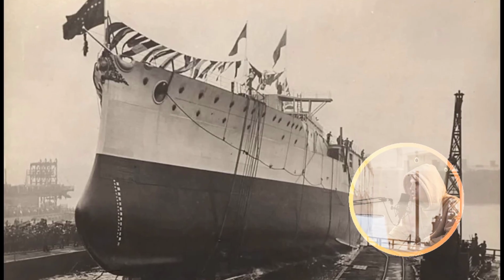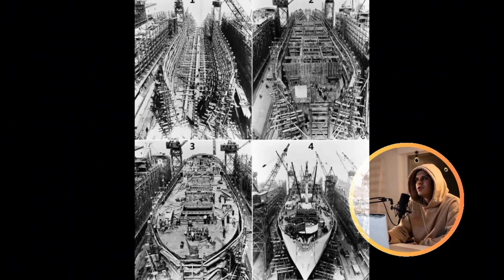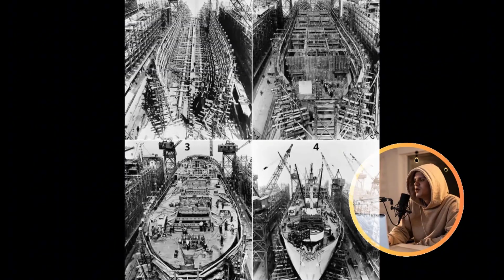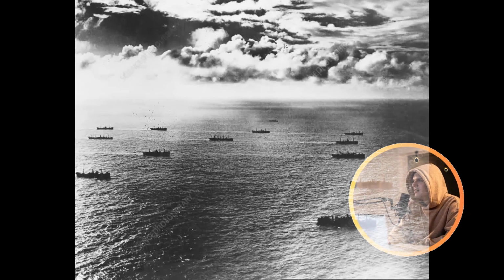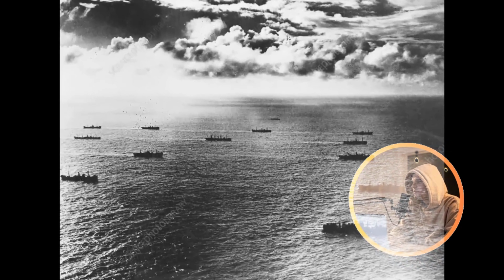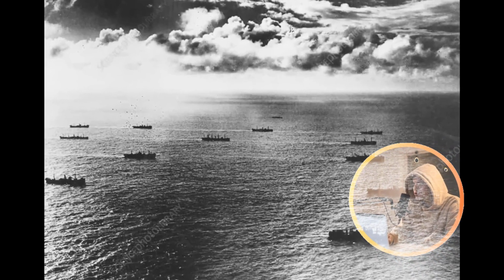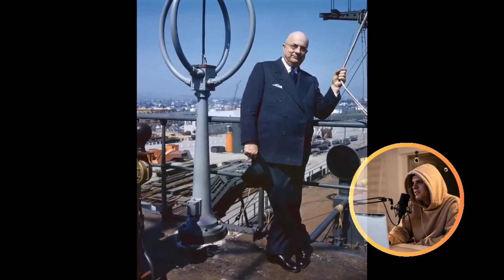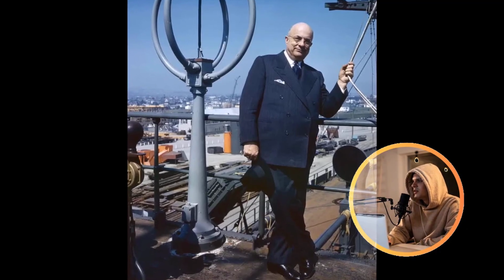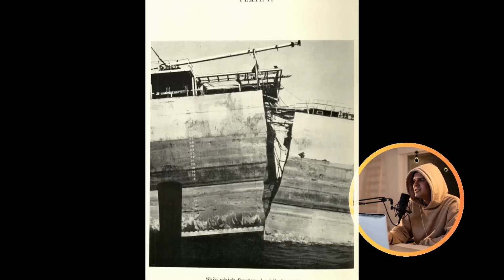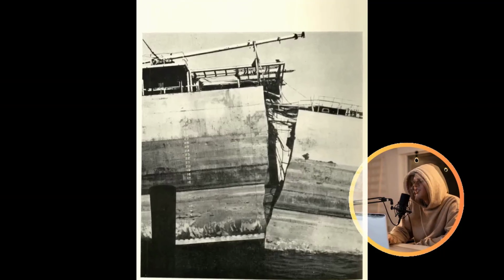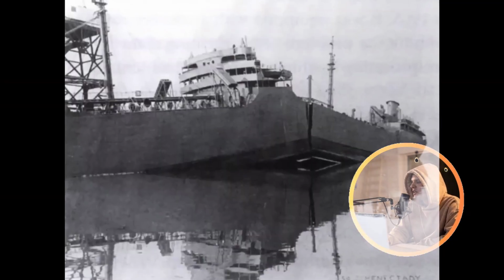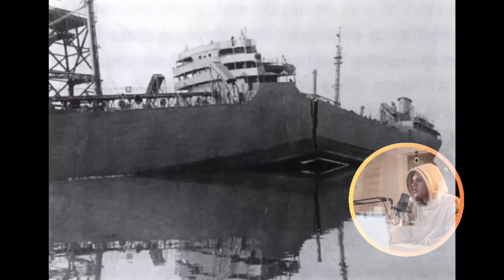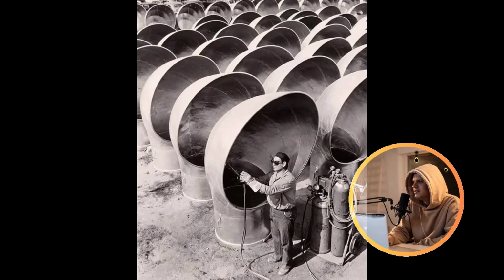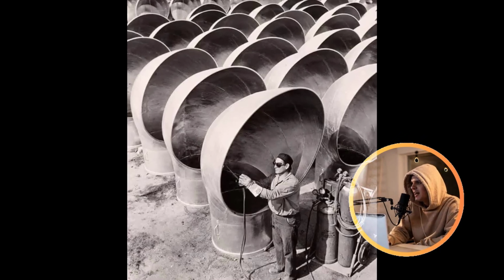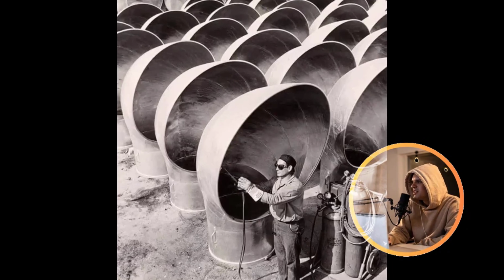Quality control, in this new era of shipbuilding, became nothing short of obsessive. Every completed weld underwent meticulous magnetic particle inspection, a refined technique where finely dispersed iron powder, under the influence of magnetic fields, would visibly reveal even microscopic cracks invisible to the naked eye. Ultrasonic testing was employed to scrutinize internal weld quality, guaranteeing full penetration and the absence of any hidden voids or imperfections. X-ray inspection was reserved for critical structural welds, producing invaluable permanent photographic records that attested to the absolute integrity of each weld.